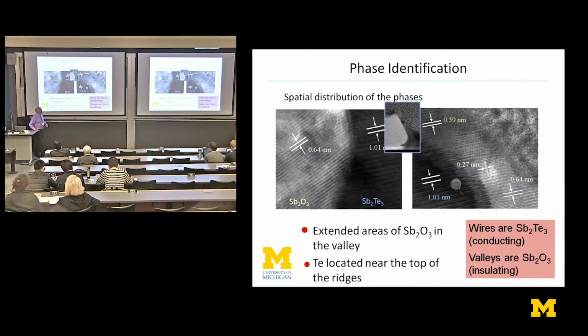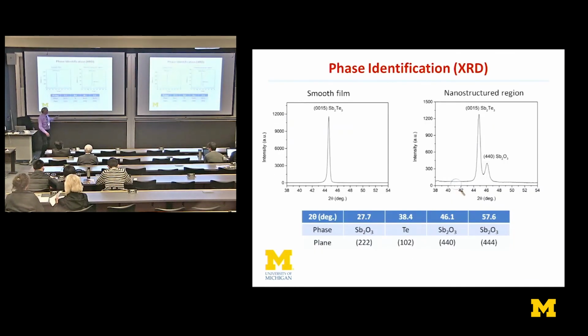So there are a lot of details here. How do we know? We got antimony oxide instead of antimony telluride in the space between the wires. In other words, an insulating valley. We do very detailed phase identification from the transmission electron microscopy, looking at lattice spacings, matching those to compounds that are formed. We also do a lot of X-rays to back that up. So we see X-ray peaks from antimony oxide, and also, of course, from antimony telluride from the wires themselves.